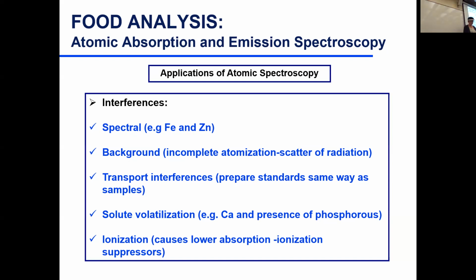Volatilization, you did that in the lab. Some of you will do that on Wednesday. For calcium, we added a reagent called lanthanum chloride. Lanthanum chloride is added so that calcium and phosphorus don't form large molecules. So if you have calcium and phosphorus in your sample, they're going to form calcium phosphate. And not just calcium phosphate, they're going to form calcium pyrophosphate, which is a cluster of calcium phosphate molecules bound to each other. So that big cluster of calcium phosphate will precipitate down, no matter what the concentration of the acid is, they're going to precipitate. So when you aspirate your sample, calcium will not be aspirated into the flame, and you end up with underestimation.